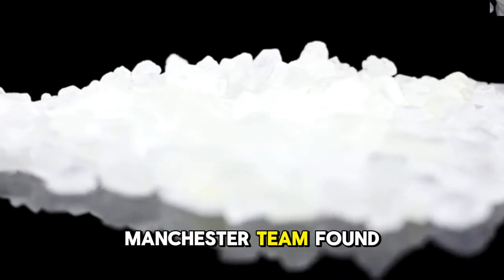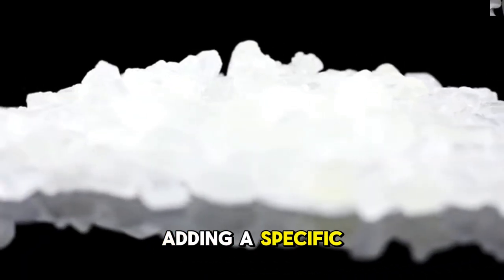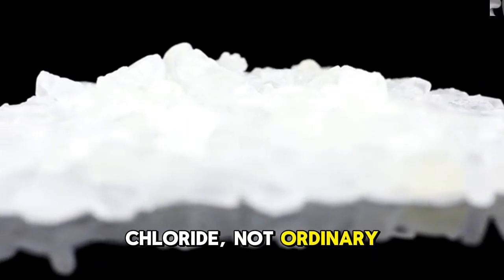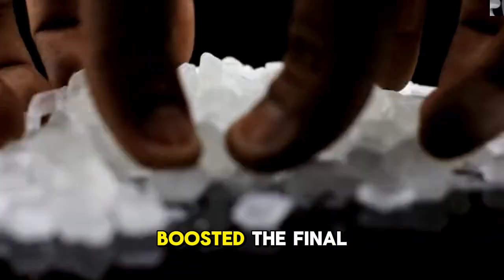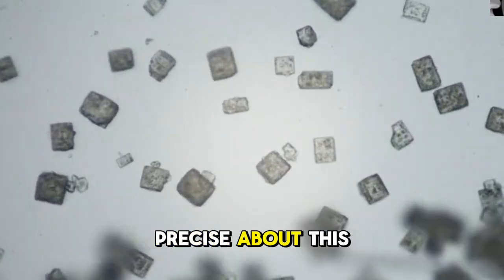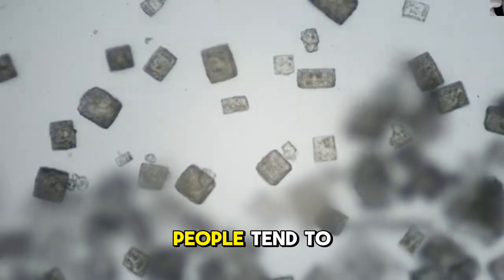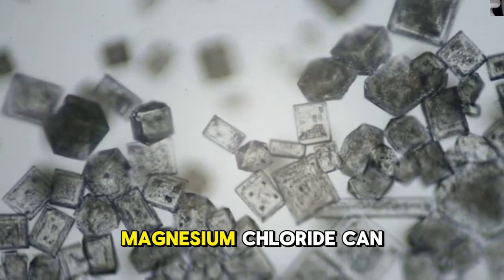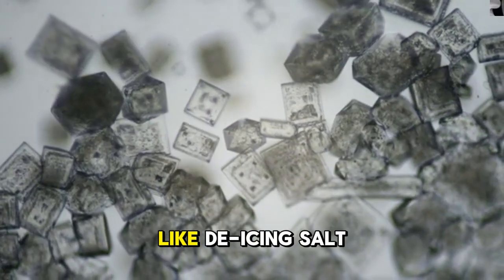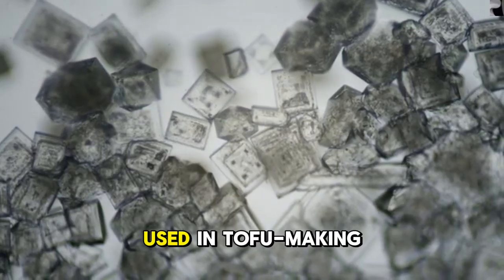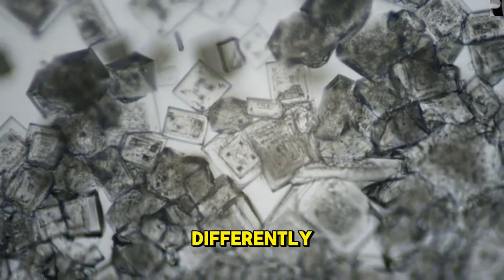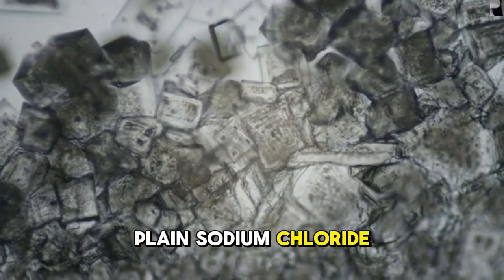Here's where the Manchester team found something extra. Adding a specific salt, magnesium chloride, not ordinary table salt, significantly boosted the final strength. It's worth being precise about this because it's the one detail people tend to blur. The researchers' magnesium chloride can come from sources like de-icing salt or nigari, used in tofu making, and it behaves differently in solution than plain sodium chloride does.